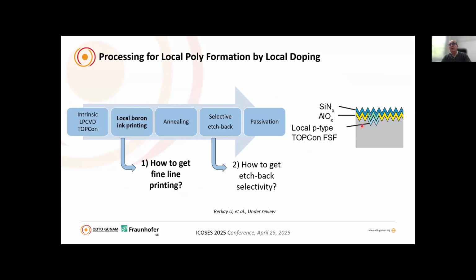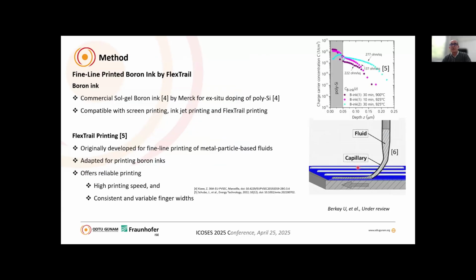Okay, how do we pattern the front side poly layer? To do this, we first produced the poly layer on the front side, and then we printed the boron ink locally, somehow. I will come to that point. The boron ink provides high doping. Then after annealing, we etched back the remaining part, because heavy P doping provides quite high resistance to the potassium hydroxide etching. So this is not etched away during the etching process, but the rest of the emitter region is etched away. In this way, we have been able to pattern the surface.